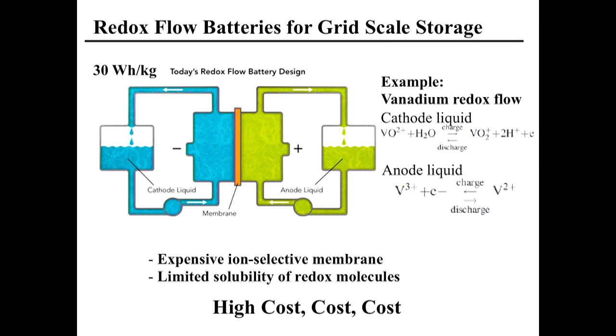This is a famous redox couple called vanadium. Vanadium from oxidation state of 5+ to 4+, 3+ to 2+. One liquid is going from, for example, 3+ to 2+. That's right here, that's anolyte. This will be here. So you flow the liquid in. This is your battery, and you store energy. You store this liquid. In order to use the energy, you flow it back, and that's a highly scalable method.